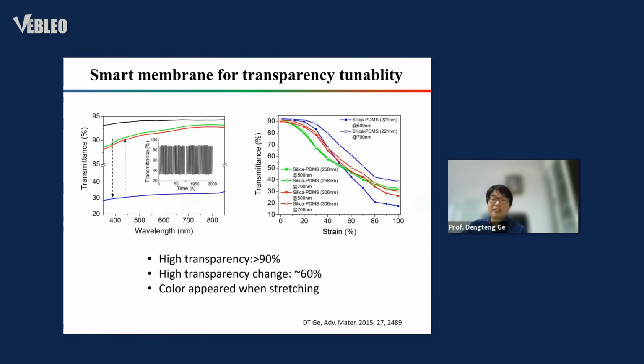And due to the narrow voids, the transparency change will be very high. It's like a 60% change, and the initial transparency is higher than 90%. Also, one thing we found is that its opacity only changes at 40% strain. The sensitivity is not very good. Only when the strain is higher than 40% can we see the color change.